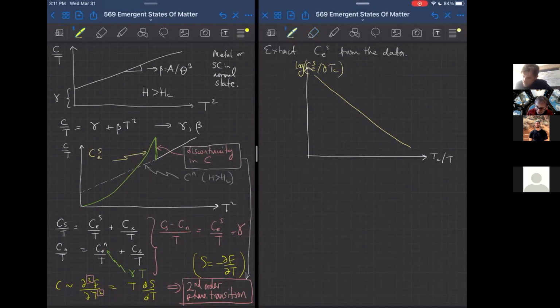And so what that tells us is that the electronic heat capacity at low temperatures has the following functional form. It goes like some number A times e to the minus b Tc over T. In other words, it has this sort of activated form. And typically A is of order 10, B is of order 1, something like that. So this exponential behavior of the heat capacity is interpreted in terms of an energy gap.